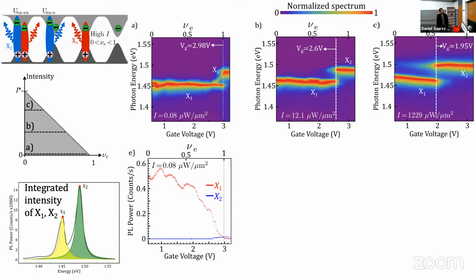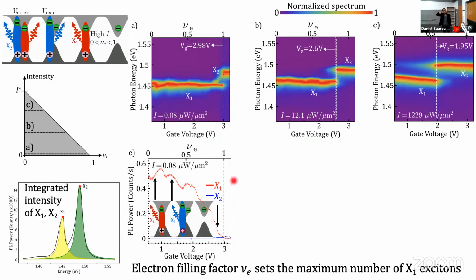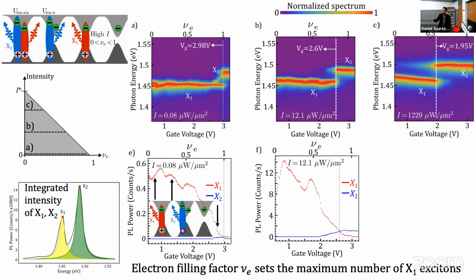So by monitoring the relative intensities, we can have additional insights into the problem, because when we change the gate voltage, we can notice how the photoluminescence from X1 actually quenches. The way to understand this is we have an initial number of excitons in our material that we're going to keep constant over the full range of gate voltages. And then as we start modulating the population of fermions, some of the lattice sites are going to be occupied by electrons. And in the limiting case, there are no more empty sites for excitons to form. So now the next exciton needs to be formed in an already occupied site. And this is the effect in the emission of X1.